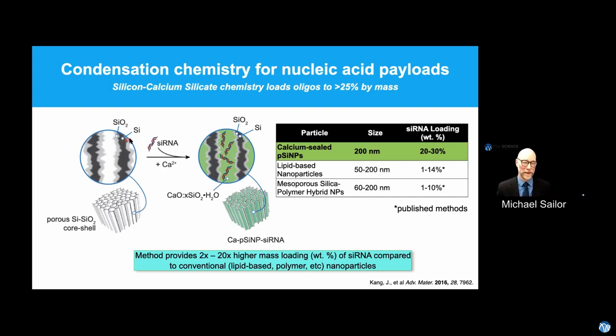The silicon nanoparticles that we make, as I mentioned, have a core that oxidizes fairly easily in water to SiO2, silicon dioxide. In the presence of the nucleic acid, this highly negatively charged molecule that normally doesn't want to pack into those pores, we tried the same condensation chemistry that had been played with for decades. We just added some calcium chloride to the solution. And lo and behold, the calcium ion paired with the nucleic acid and helped it pack into the particles to a very high concentration, because those negatively charged strands were not repelling each other as much. And we got a benefit: as the silicon dissolved locally into silicic acid, the SiO2 started to dissolve, and it immediately precipitated with the calcium. Basically we cemented our nucleic acid into the pores with this concrete chemistry.